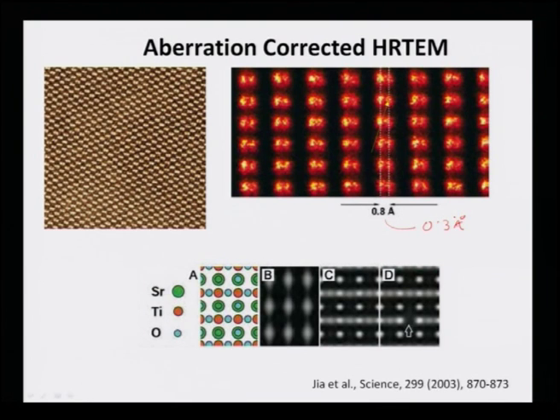So by using simply a CS corrected microscope, as I showed you in the first lecture on HRTEM, we can even image the oxygen atoms in strontium titanate. It has been reported by Jia et al. in Science 2003, and now it is a routine thing. People can actually image oxygen, nitrogen, even carbon atoms, which are very small, because resolution limits are reached, that is, a value of 0.3 angstroms is very easy to achieve.